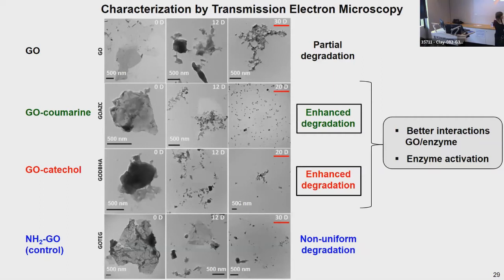While for the amino graphene oxide used as control, the degradation was not uniform, in the sense that there were sheets that were degraded or partially degraded and some that were not degraded. So you see here that by proper derivatization, we could enhance the degradation because we could somehow favor the interactions between the graphene oxide and the enzyme.